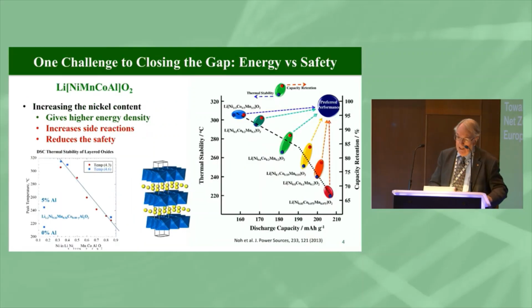And to get even higher with these layered oxides, we've got to go to higher and higher nickel contents. So what we want to do is push the nickel as high as we can. At the same time, we want to lower the cobalt as much as we can. The cobalt's the most expensive element. There's child labor issues there in the Congo. And right now, China dominates the cobalt. Essentially, all the cobalt goes through China to be processed.